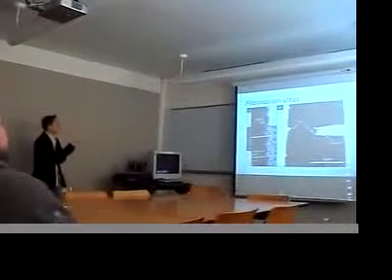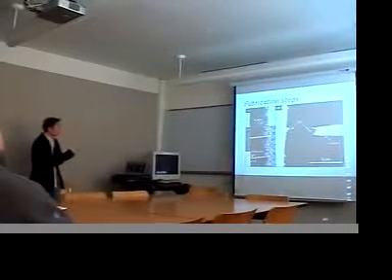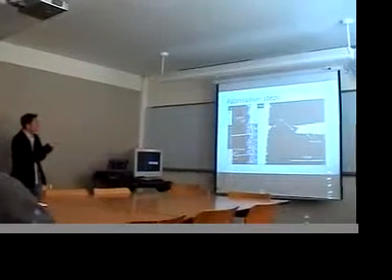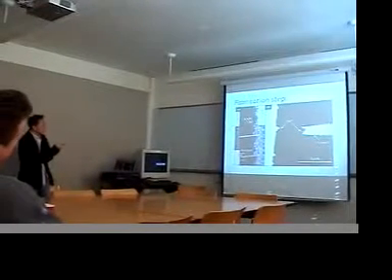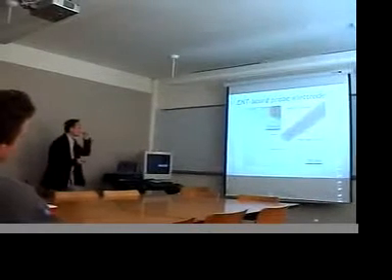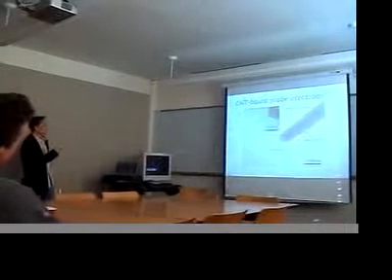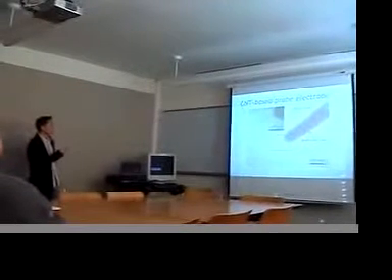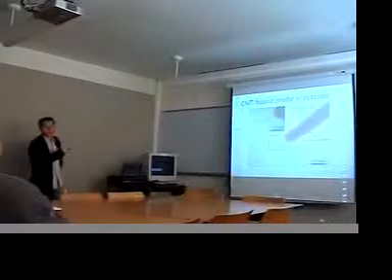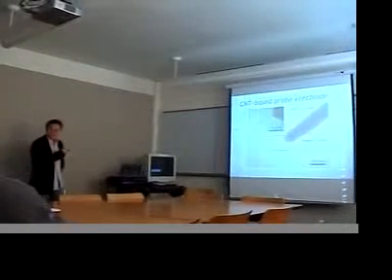So you have a carbon nanotube connection, you deposit parylene, and then you heat this guy up, and sure enough, it detached, and you can see this carbon nanotube hanging out with parylene around it. And this is probably the best picture you're going to see all day. You can see very clearly a carbon nanotube sticking out with the parylene wrapped around it. So the goal is to have this part inserted into a cell. That's the angle.